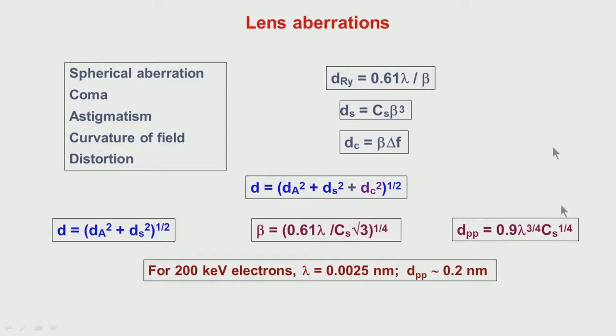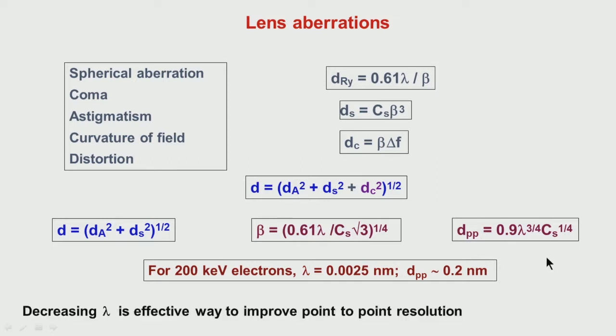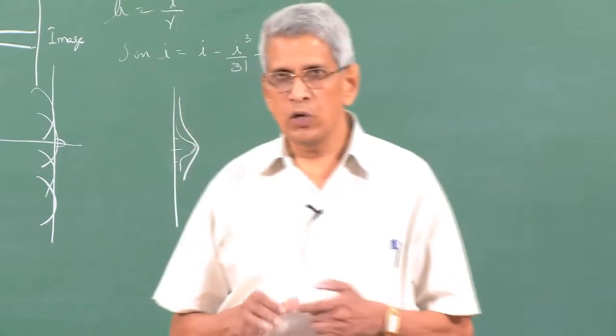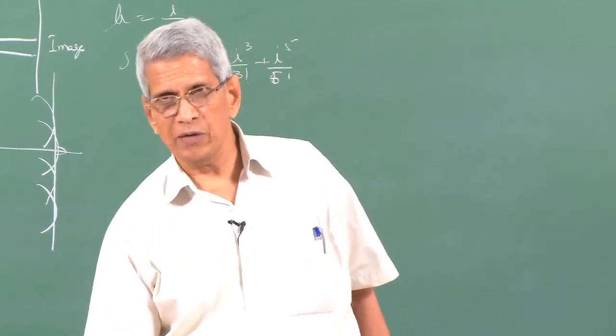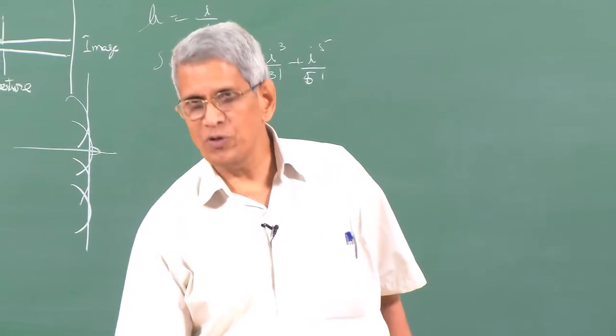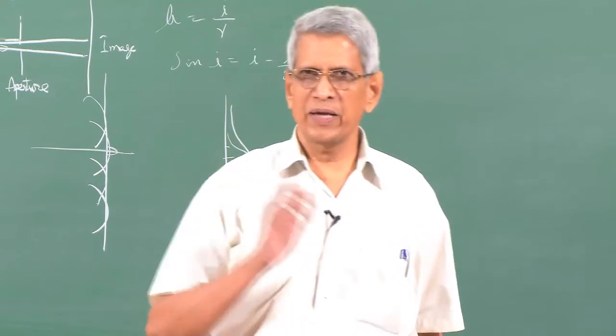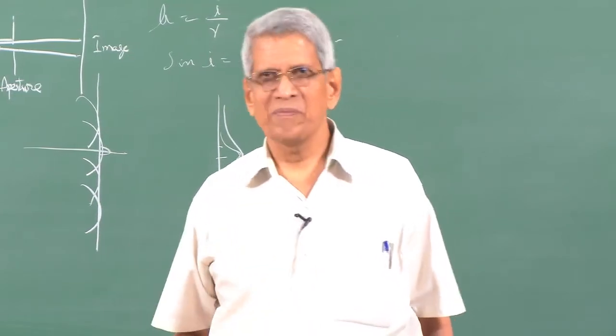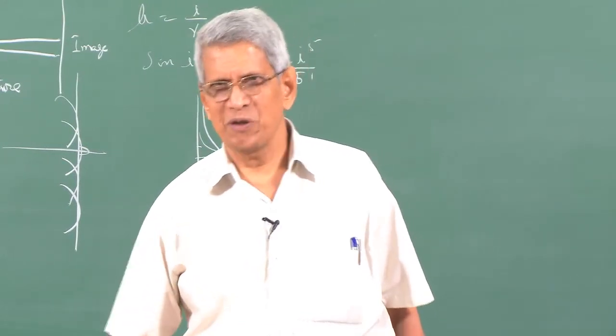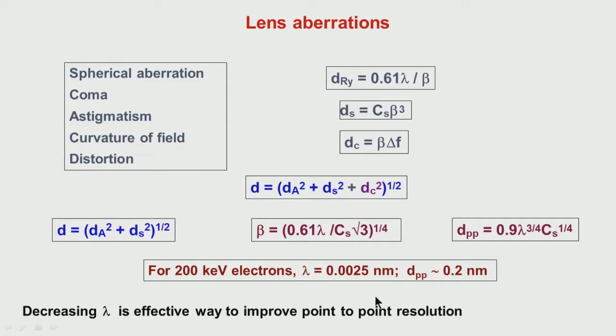So this simple derivation shows how exactly one can calculate the effect of different aberrations on the resolution. And in fact, by decreasing lambda, we can improve the resolution. That is what was done initially, and that is how people started making high voltage microscopes. There are 1 million volt microscopes, 3 million volt microscopes, 2 million volt microscopes, where resolution becomes much better. The other option which has been adopted now is that if you can make the spherical aberration small with the same normal operating voltage, you can still get the best resolution. Those microscopes are called aberration corrected microscopes.